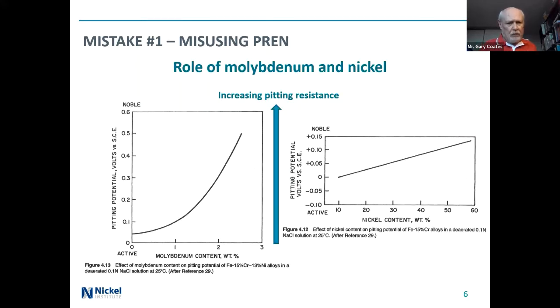So let's look at the effect of molybdenum and nickel. The curve on the left is the effect of molybdenum content on an alloy, and it's measured in terms of pitting potential, but we can say increased pitting resistance is really what it's measuring. 1% molybdenum doesn't do an awful lot, but 2% and 3% do very much for improving the pitting resistance. On the right is a curve for nickel. You can see the scale of the content of nickel on the bottom there, that there is a slight improvement in pitting with increasing nickel content, but nothing like what it is with molybdenum. So it is positive, but a very, very small effect. And for that reason, it's left out of most PREN formulas.